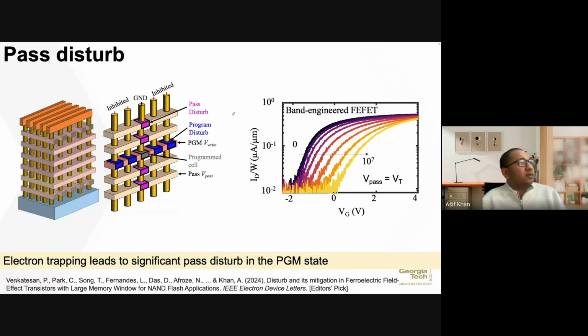So, to our not so much excitement, what we saw is that when the device is in a certain state, for example in this low VT state, and we apply a pass voltage, which is around 4 volts, as you keep on applying these pulses, this threshold voltage keeps on shifting. And it is a large shift from minus 1.5 volts to approximately 1.5 volts. We apply this voltage for around 10 power 7 cycles. And this was a big challenge for this device.